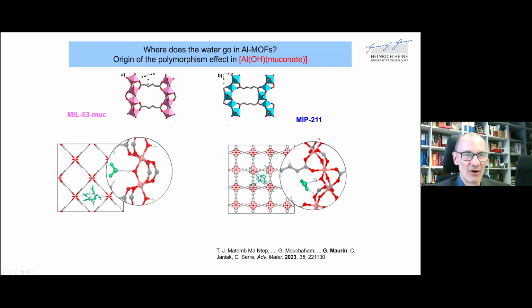Whereas in the MIP-211 polymorph, as you can see here in this scheme, the water group can not only accept an H bond from a hydroxyl group, it can also donate a hydrogen atom to a hydroxyl group. So it at the same time enters into two hydrogen bonds, and thereby it has a much higher binding energy than in the MIL-53 muconate polymorph. And that gives this polymorph the much higher hydrophilicity. So this simple, small change of a trans versus cis orientation is the basis here for this difference.